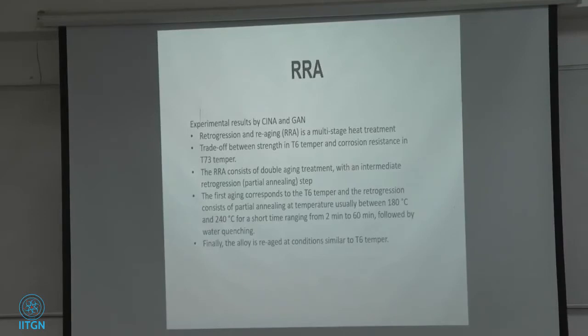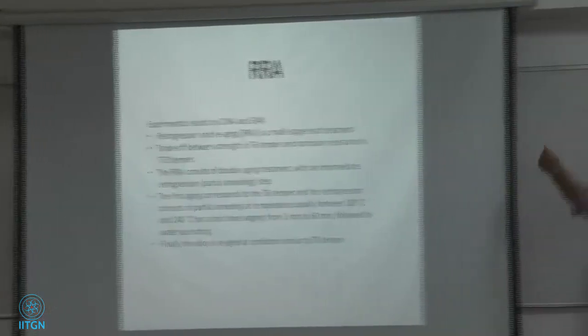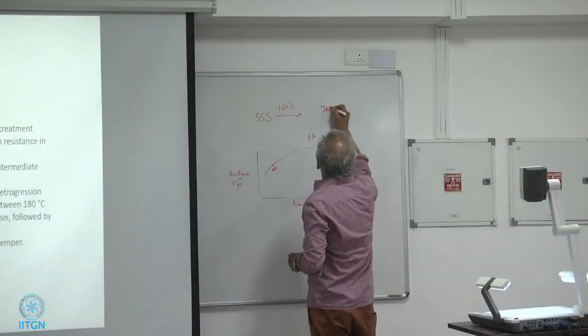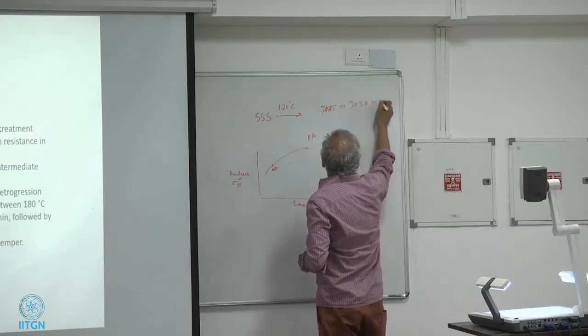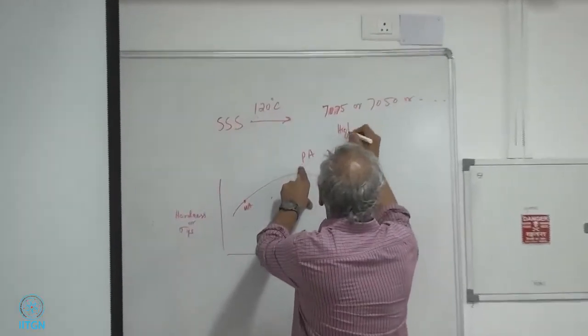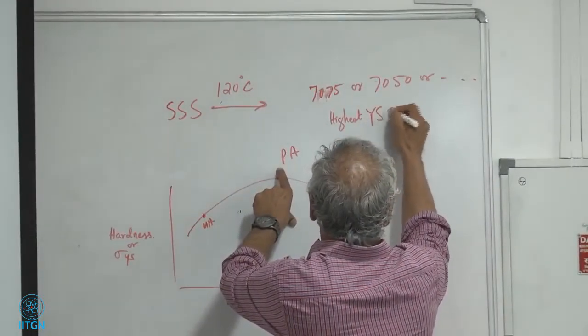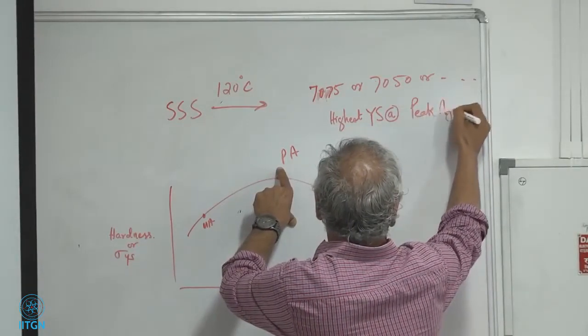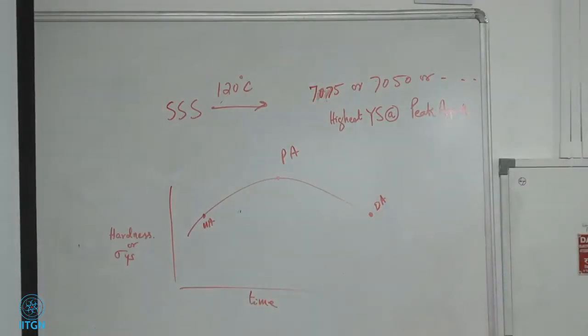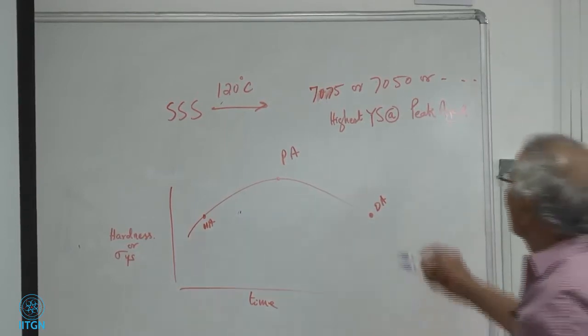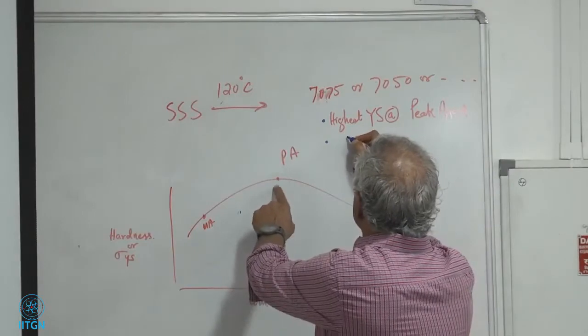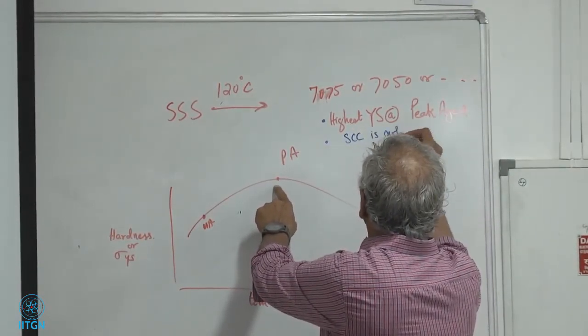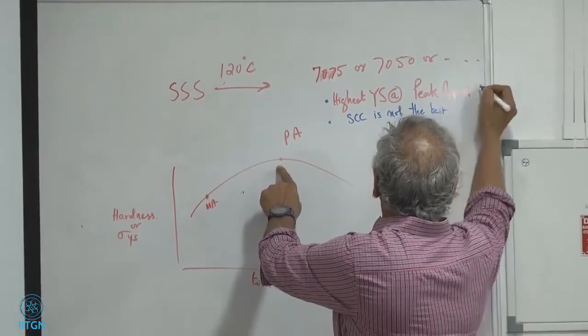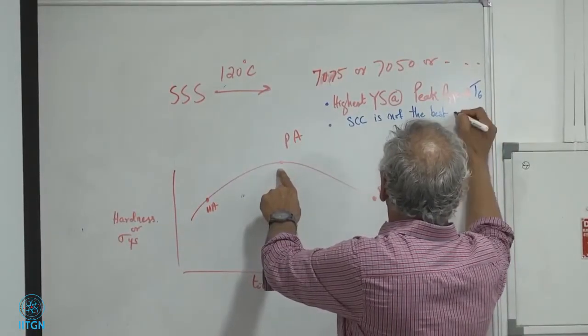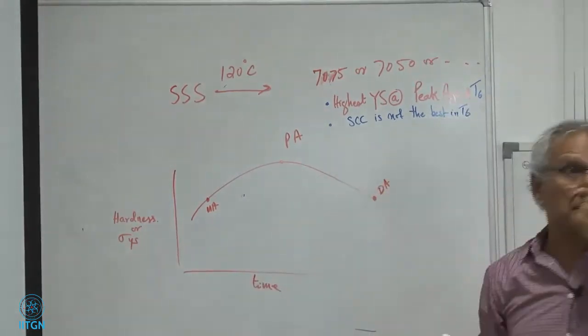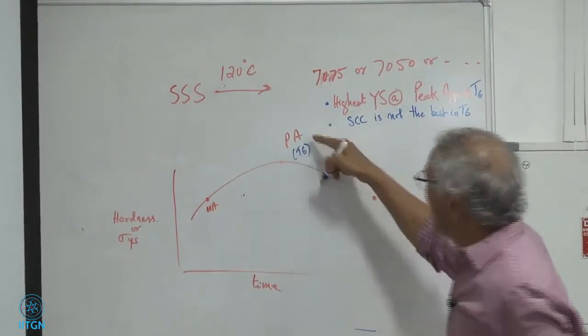So it so happens, aluminum alloys or that 7000 series, let's stay with that, 7075 or 7050 or something else, highest yield stress at peak aged. Right? Corrosion, stress corrosion cracking, not the best. Let's call this T6. In T6 condition, this is my T6. Peak aged is my T6 condition.